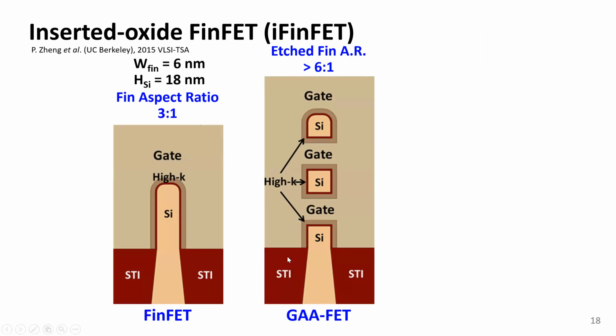So let's look at the schematic cross-section of a FinFET. It's a tall and narrow fin, and you have the gate dielectric, the high permittivity gate dielectric wrapping around it, and the metal gate. And then you have shallow trench isolation oxide on either side, just to isolate this transistor from neighboring devices. Now, with a gate all-around device, you need to insert the gate material and the gate dielectric in between each silicon channel region. And so in order to form this structure, you have to form a pretty high aspect ratio structure. And if you have fins that are closely packed together during the fabrication process, when you pattern them, they can actually end up tilting and touching each other. So it's not trivial to make fins with high aspect ratio, especially if you want to pack them closely together.